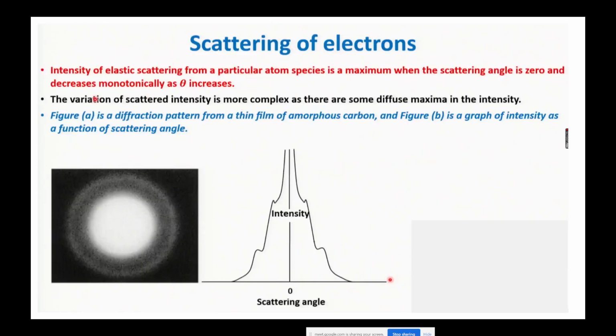Now, regarding the scattering of electrons, the intensity of elastic scattering from a particular atom species is maximum when the scattering angle is 0. Suppose your electron beam is coming and it is not scattering, then you will get a higher intensity. So here you can see at scattering 0, the intensity is higher. When you deviate from the angle, your intensity gets reduced. It is very simple because with no scattering, your intensity will be high. The same thing you can see here at the center, the intensity is higher, and when you go far from this, you will get a lower intensity.